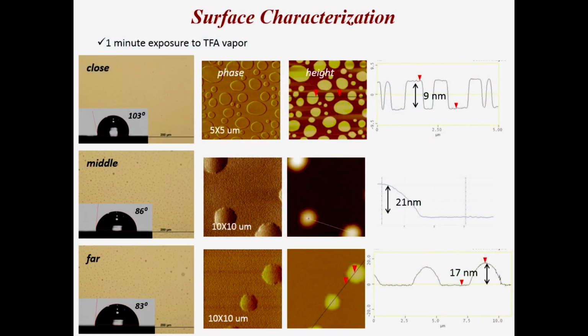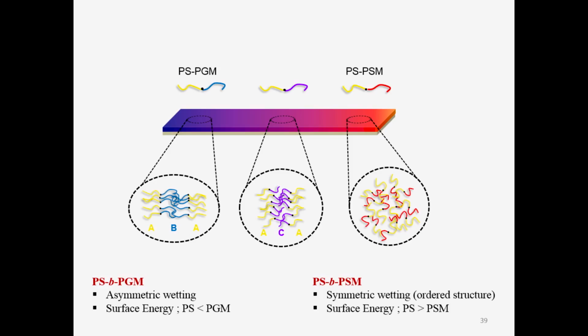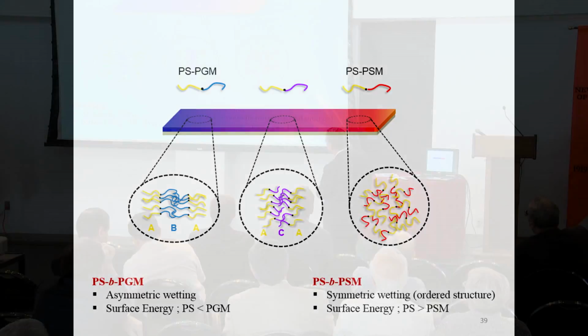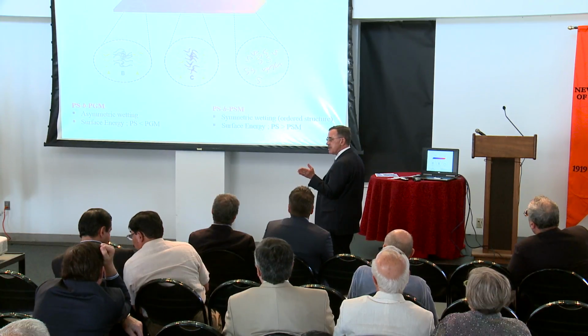And in fact, these just happen to be results where this happens to be the bottom of the film, and this is at the top of the film. This is disordered, this is ordered. And effectively what we're able to do then is take films and generate structures whereby we have a disordered film on one end, ordered film on the other, and in the middle we have something that's intermediate, but that actually allows us to take this ordering front and to propagate it across the surface.